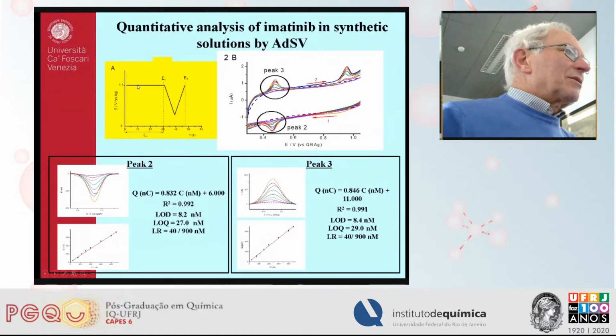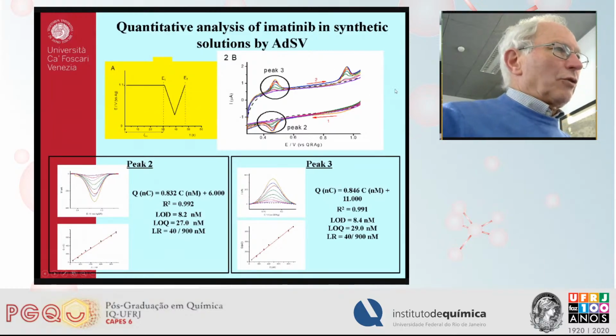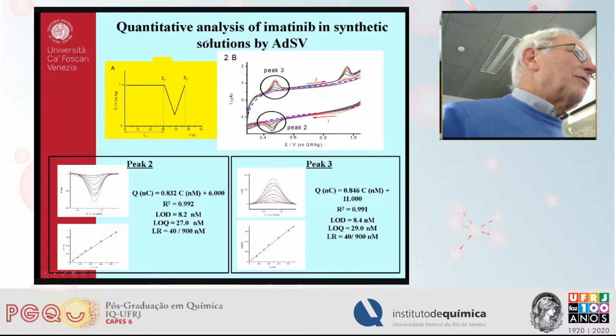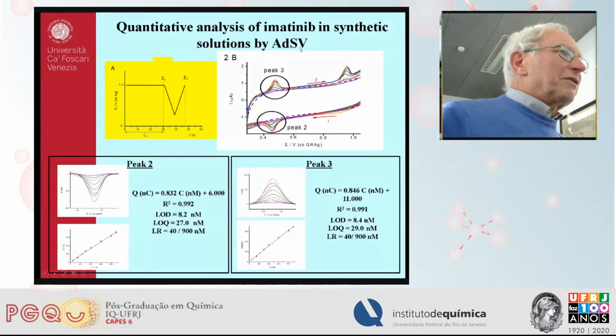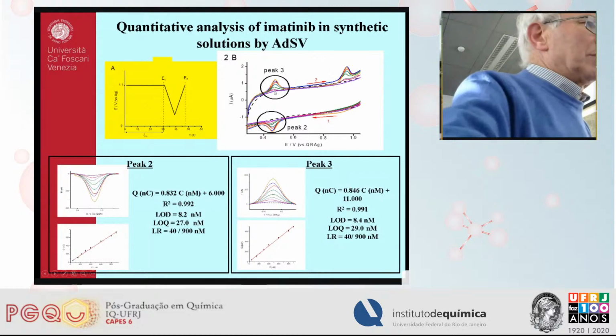In order to increase the sensitivity with the technique I showed you before, we used a small variation of the technique, which is called adsorptive stripping voltammetry, which means before applying this waveform here, we apply a constant potential for a short time. The time was varied between about 10 to 30 seconds. So we started the scan from this potential here. We went in this direction before, and then we went back. So you can see here the two peaks, peak 2 and peak 3, which are those we used for the quantification.